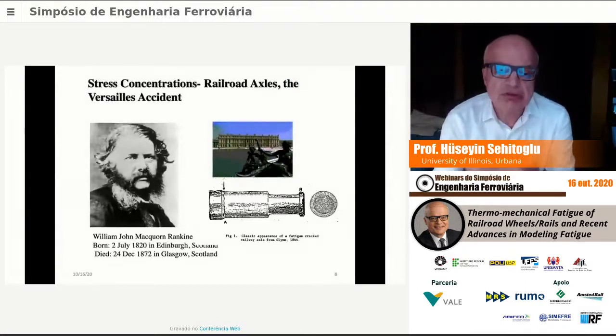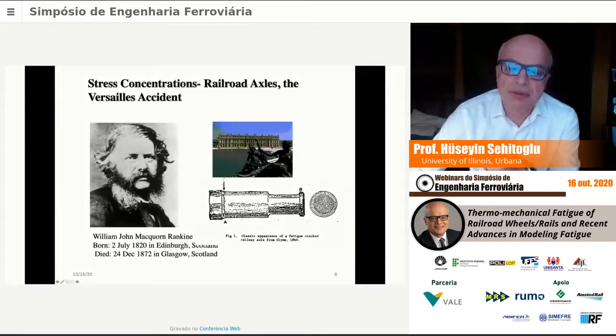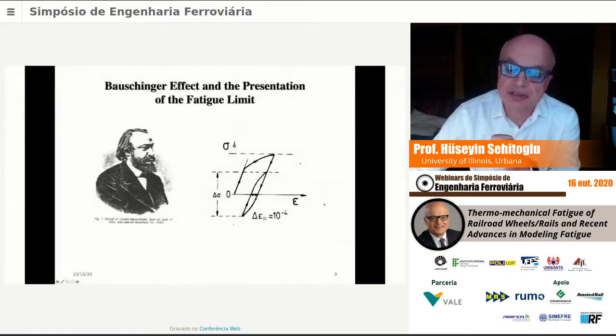Of course, the research on fatigue goes back a long time, and one of the earliest examples of fatigue occurred in 1844. I'm showing with my cursor, I hope you can see my cursor here, the failure at the fillet here in a railway axle. And this problem caused a derailment in Versailles in France. Some of the people who studied the fatigue of this railroad axle was the famous Rankine, more famous for the thermodynamic Rankine cycle. And you could see here on the fracture surface that there is a fatigue crack zone, and then the final fracture is in the middle.